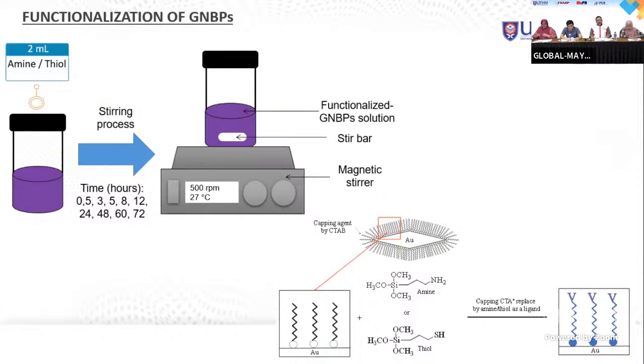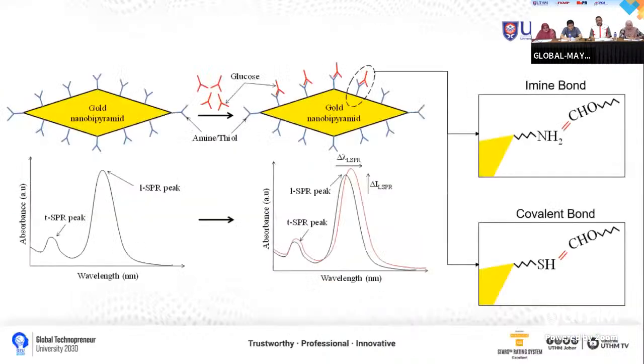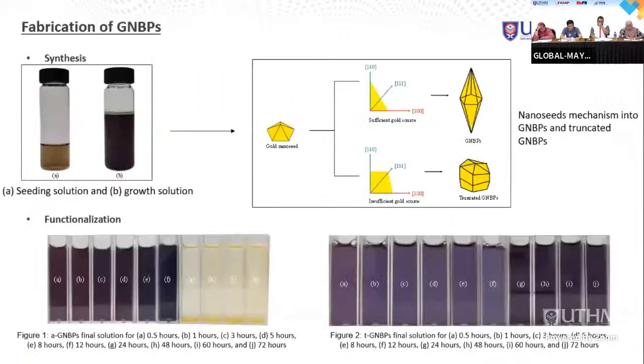Note that GNBPs are covered by a CTAB layer, or cetyltrimethylammonium bromide, before functionalization, used as a capping agent in the seeding and growth process in the earlier synthesis. But after functionalization, the CTAB layer will be replaced by amine or thiol groups. Here is the illustration for the role of amine and thiol on the GNBP surface. The binding between amine and glucose is called imine bonds, and for thiol it is called covalent bonds.